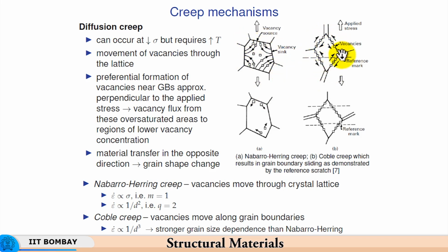So, grain boundary diffusion is much faster, much more effective in relatively low temperature creep, which is Coble creep, and so grain boundary sliding takes place here. Grain boundary sliding will also take place over here. The grain boundary sliding will also take place over here, but then in addition to the diffusion along the grain boundaries, there is diffusion through the lattice as well in case of Nabarro-Herring creep. Now, the typical situation in creep is that